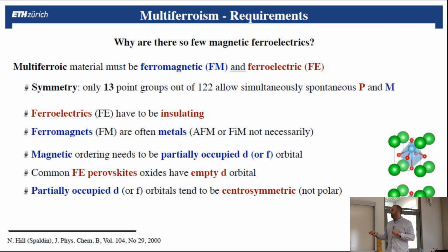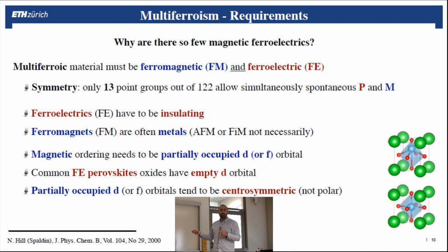On the other hand, for ferroelectricity, most of the ferroelectric materials in the Perovskite structure that I showed here have empty d orbitals, which is contradictory with this. And more than that, if you have partially occupied d or f orbitals, then the structure tends to be centrosymmetric, which means non-polar. So for example, this would be a centrosymmetric structure, and this would be a non-centrosymmetric one, which will have the polarization.